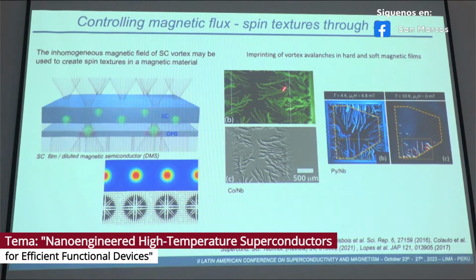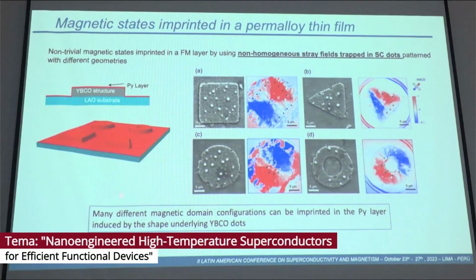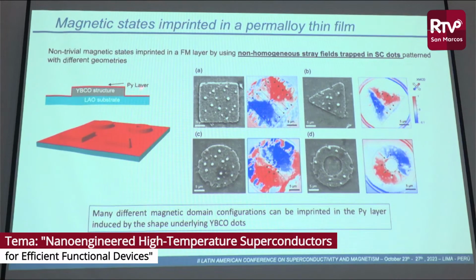Okay, so in this work here, they were able to imprint vortex avalanches in different magnetic systems, and the avalanches generated in the superconductor could be seen when removing the magnetic field in the superconductor, and could be imprinted in the ferromagnet. With this idea, we also try to work in systems combining high-temperature superconductors with ferromagnets. And in this work here, what we did is to nanostructure different dots of a superconductor, YBCO superconductor, and the shape of the dot could completely control the imprinted structures in the ferromagnet.